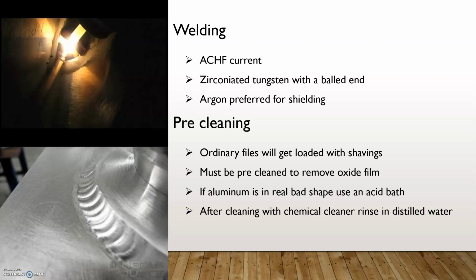Moving on, alternating current high frequency is done with preferably a zirconiated tungsten that has a balled end. Argon is widely used for shielding. The oxide film on the material must be pre-cleaned for welding. If files are being used, ordinary files tend to get loaded with shavings. You can coat that file with soapstone to reduce that, or get a file that has wider grips in between it. If acid cleaners are used on dirty parts, those parts must be rinsed with distilled water for safety reasons, obviously.